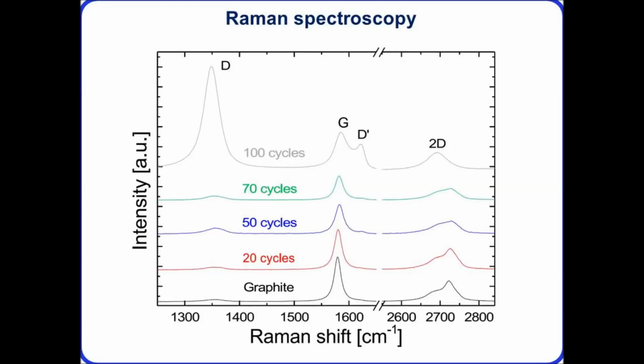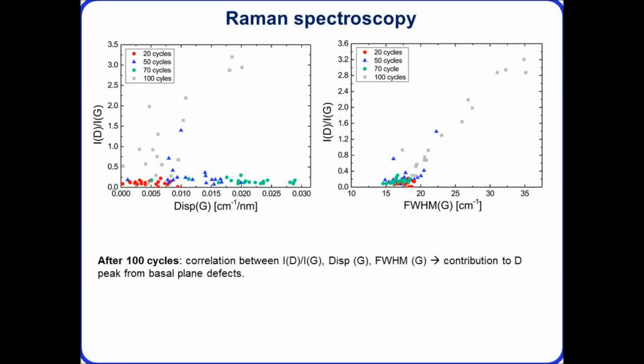When we do some further study, and this is probably the main expertise of our research group, this type of spectroscopy, you find a correlation between the intensity of the D peak and the G peak, which you can call the graphite peak. We attribute that to the fact that we are starting to put defects or functional groups into the surface of the graphene, rather than at the edges, and the basal plane plays a key role in properties such as the electronic and mechanical properties. So this is quite a critical piece of understanding, that we don't need to process more than 70 cycles. If we do, we start to degrade the graphene material.